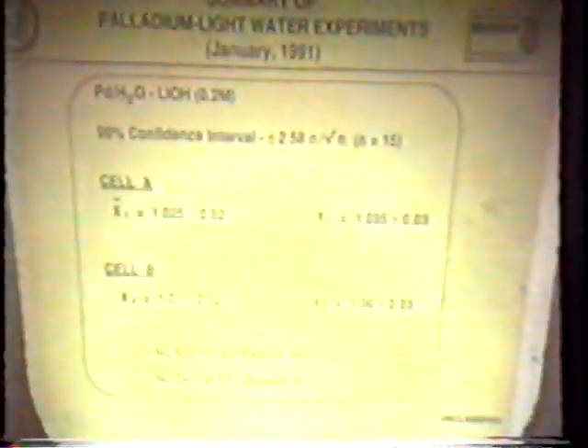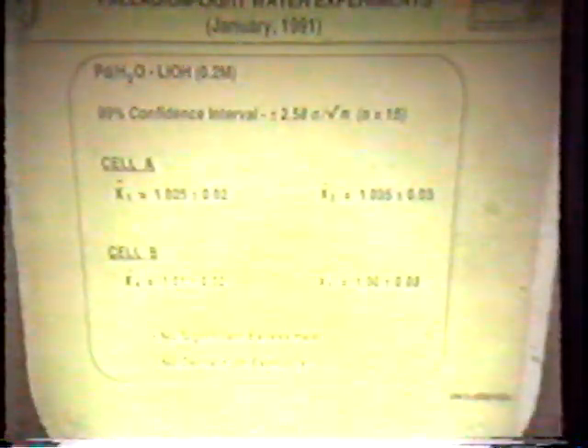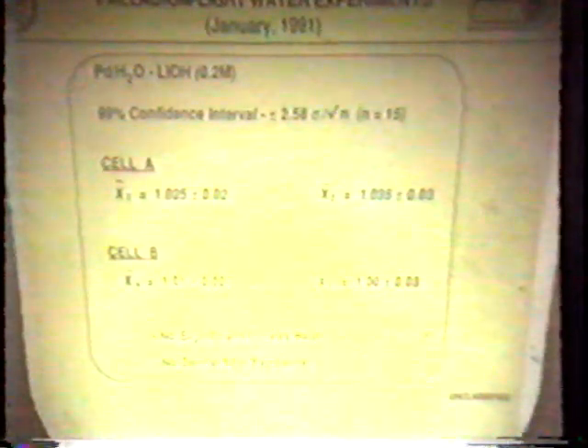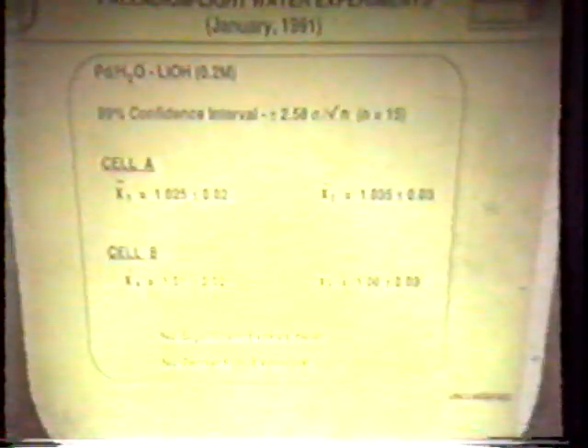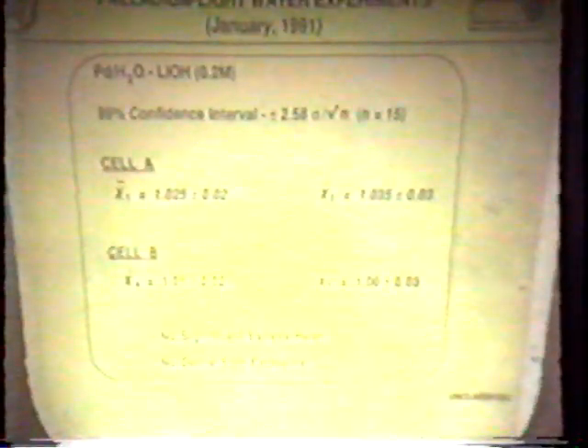The light water experiments that we ran in January, when we wrote the preliminary note, we thought we had some evidence for excess heat, but we found that was because we were running experiments with dental film, and the liquid level in the gap was not where it should have been. But going back and recalculating that, we found that in the light water cells, we really didn't have excess heat either. Within our standard deviation, we were within break even on the light water cells. We did not get heat, we did not get dental film exposure, and we did not get any helium-4.